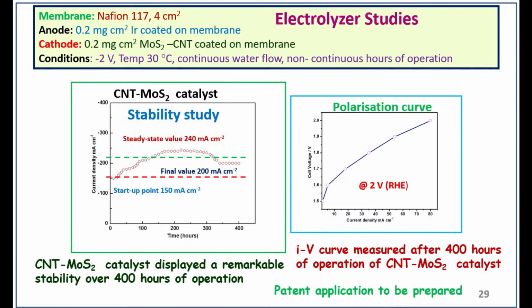Now I have cell data of 1000 hours of operation. So it looks quite good for me. 250 milliampere is quite good, because it is one quarter of the platinum value. But the CNT cost is still a little bit higher, so we want to replace it with our own carbon, which is going on in our laboratory. What I am saying is, this material is stable. The MoS2 is stable. We can use it for large scale hydrogen production if we prepare a good catalyst in large scale quantity in our laboratory.